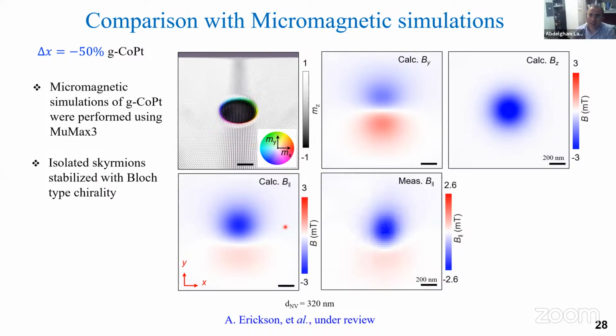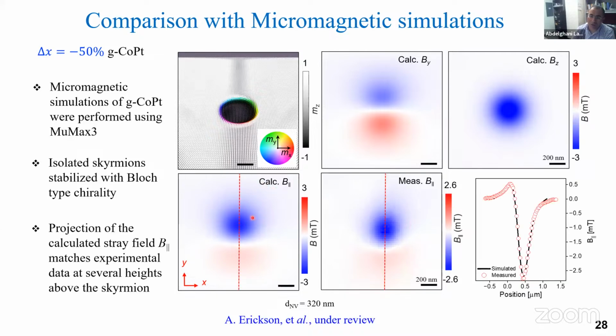And in fact, they did, because this is the projection along X, Y and Z. Also, one can measure the projection of the stray field created along the NV axis. This is the calculated and this is the measured. If you now compare the calculated and the measured one, you see a perfect agreement. In this case, what we are changing is just the position of the NV relative to the skyrmions. This is a lateral cut, but the fact that you have very good overlap shows how good the NV is for determining the stray field generated from these isolated spin textures.